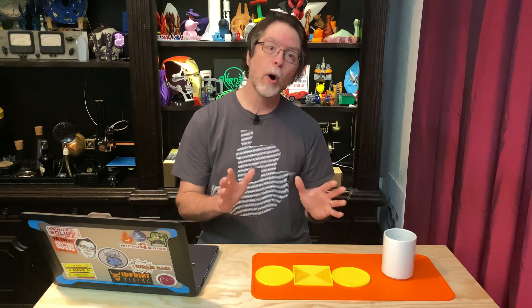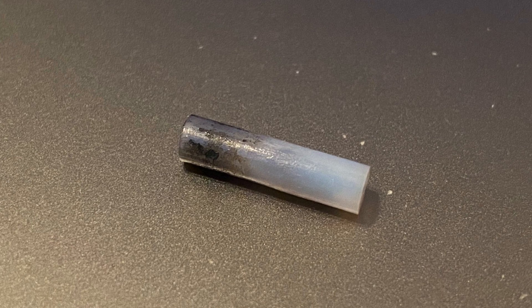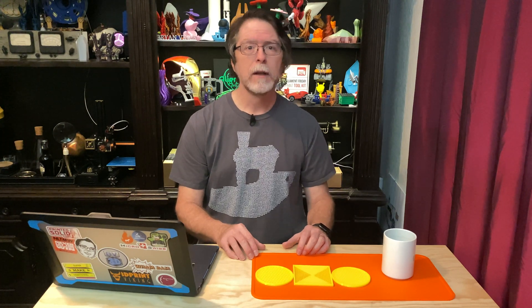And I learned something when I did that. These BMG things, with their dual filament drive gears and 3 to 1 gear ratios, can push so hard on the filament that it actually pushed the Bowden tube off the end of itself when the filament got stuck in the hot end yet again. It turns out that the reason for all the jams had nothing to do with the stock extruder not pushing filament hard enough. Clearly, if an upgraded extruder can push the filament so hard that it pops the Bowden tube out of itself, there's something else going on. And that something else was the crispy, crunchy, constricted end of the Bowden tube down in the hot end, and it got that way because of the higher temperatures I was using to print all that PETG. So in the end, the fix was simply replacing the Bowden tube.